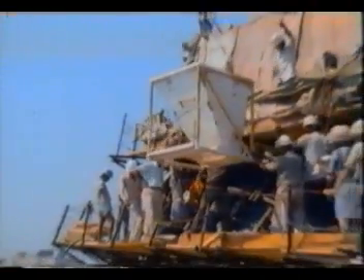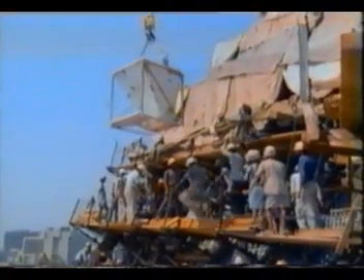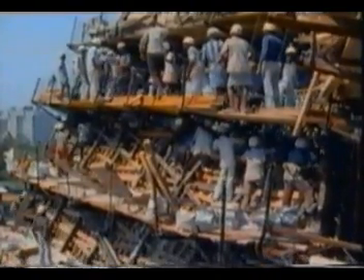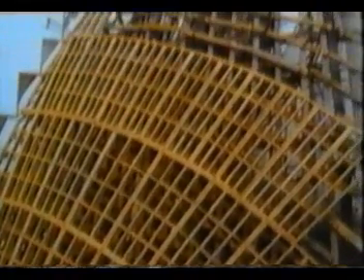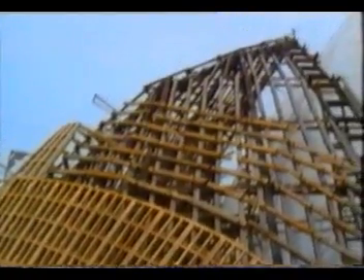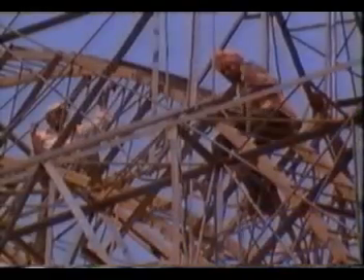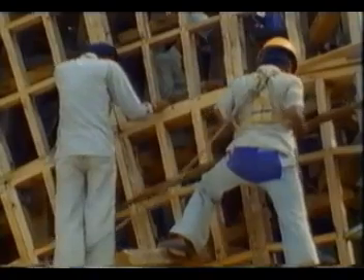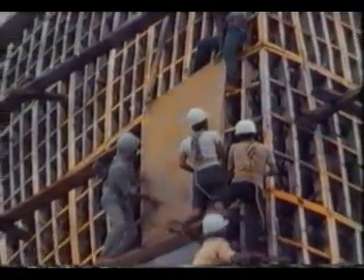Months of consultation finally produced a complex plan requiring the precise coordination of some 300 workers at a time, working rapidly, precisely, and continuously for periods of up to 48 hours. In preparation, thousands of square feet of formwork were painstakingly laid out on precise geometric coordinates and fixed to a specially designed steel space frame. The outer formwork was then systematically numbered for reassembly and removed. The inner formwork, built to furniture makers' standards, was precisely aligned and sealed. The cage of galvanized reinforcement was carefully fixed in place.